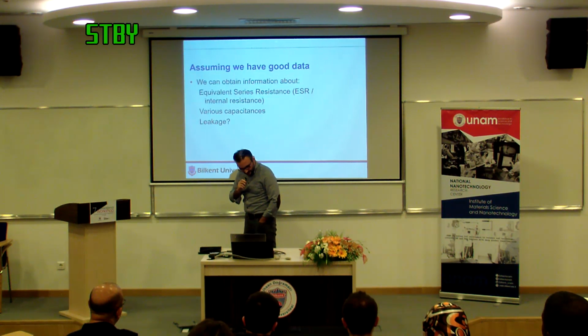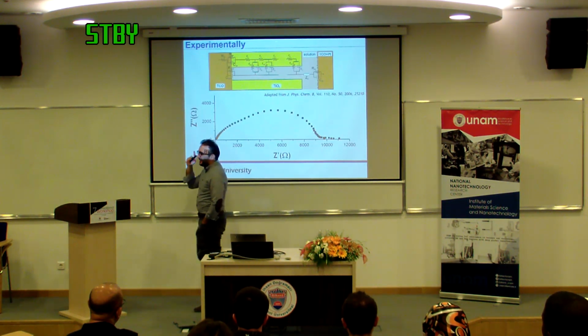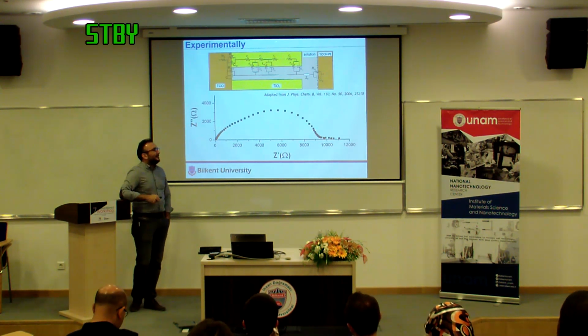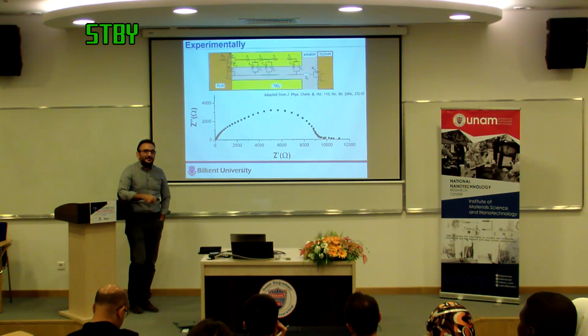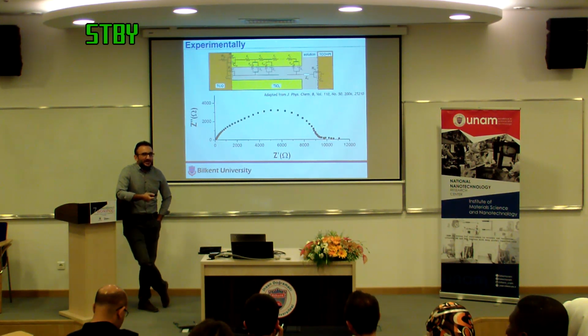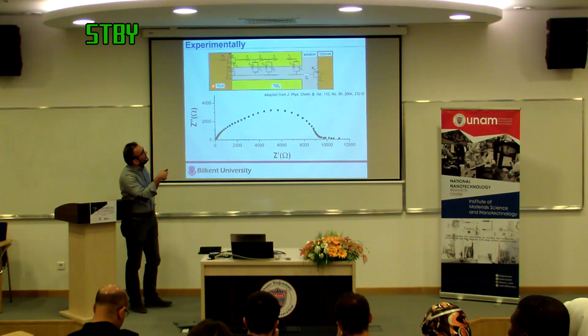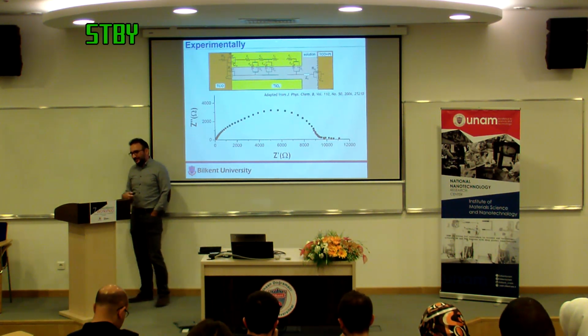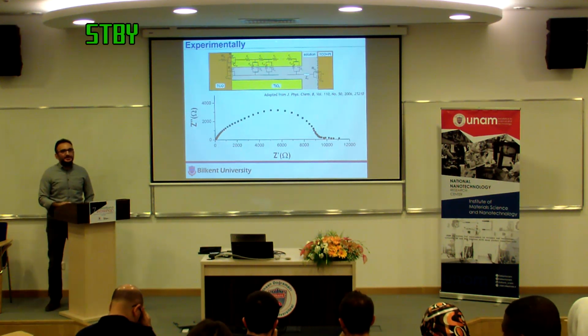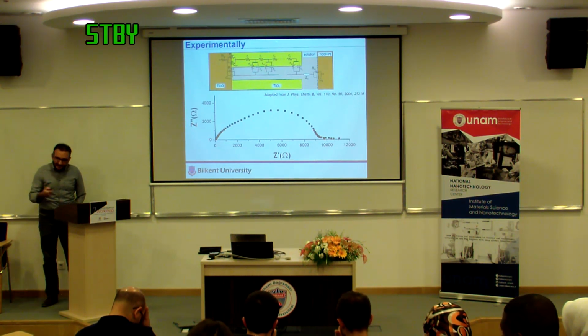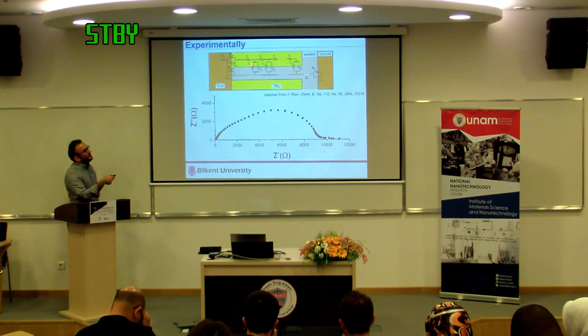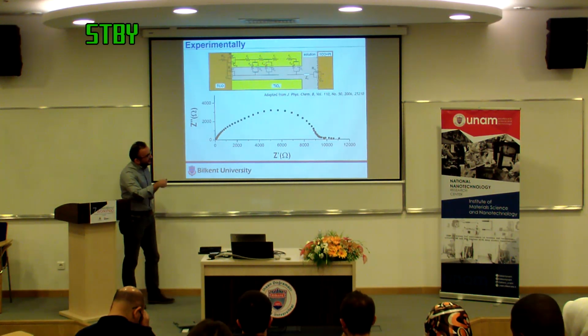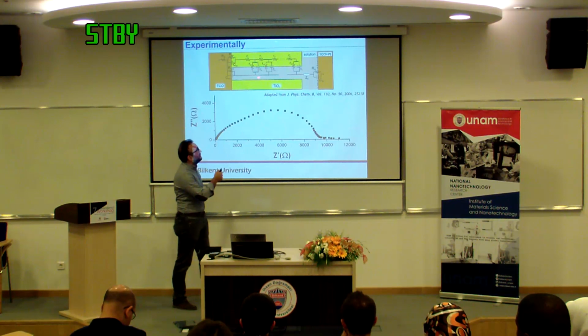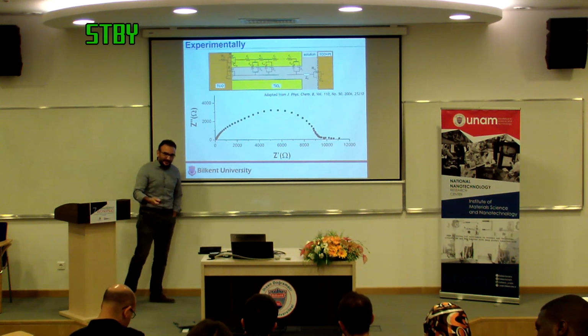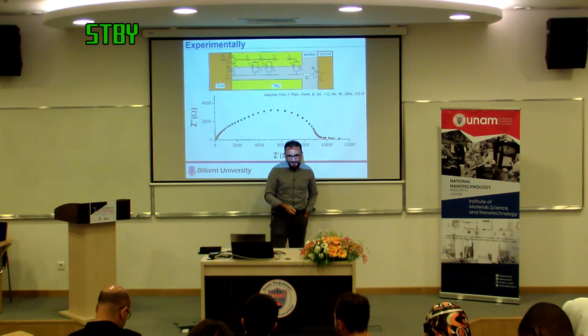So, I am missing this one. Sorry about that. What I've done is I did this fit, and then I took this exact same cell, and I've done X-ray measurements. Turns out you can actually optically measure things like recombination rate and charge extraction rate. And those correlate to various R's and C's within this model. So the only way I could trust the fit here was by verifying the parameters with independent measurements. So impedance spectroscopy is powerful because all of these bumps actually represent different interfaces in the system. But which one represents which interface is one issue. And there are probably 20 ways to fit this to this data. So identifying the correct set of parameters is an issue that needs to be tackled.